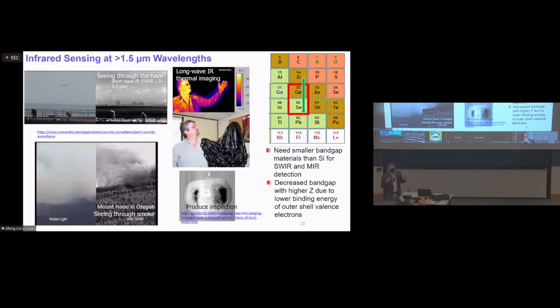An interesting thing you see is that your lenses, glasses, which are perfectly transparent in visible light, become opaque in longwave IR. That's because silicon dioxide basically absorbs light at greater than 3.5 microns. So essentially this becomes black. While the thermal radiation from your arm actually penetrates through this black plastic bag and is picked up pretty well over here.